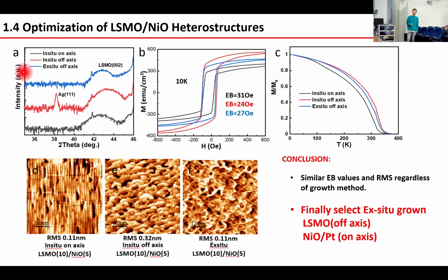Okay. So here we show the red curve of the in situ off-axis. Here shows the silver peak due to the glue. We fix the substrate on the heater, so there is some contaminant on the surface. So we also measure the magnetic property of the exchange bias with the three ways. It shows relatively similar exchange bias values, indicating similar interface coupling.